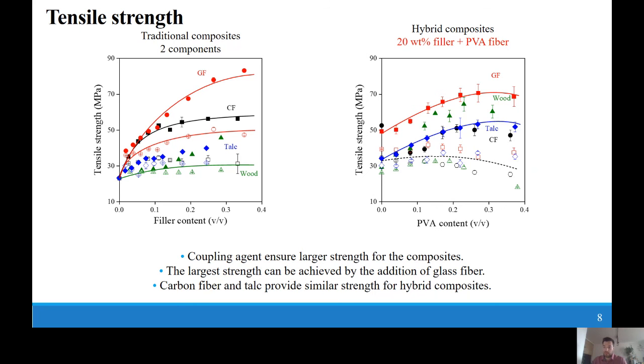On this slide, you can see the results of strength of the composites. As can be seen for both traditional and hybrid composites, a much larger strength can be achieved by using the coupling agent. The glass fiber has the largest reinforcement effect. In the case of hybrid composites, it is worth drawing attention to the talc PVA composites with the blue symbols, which have similar strengths to the high performance carbon fiber reinforced hybrid composites with the black symbols.